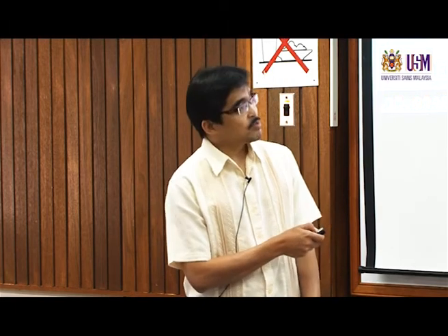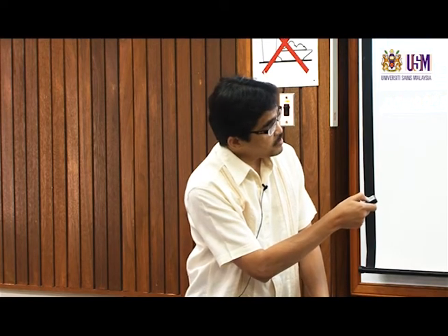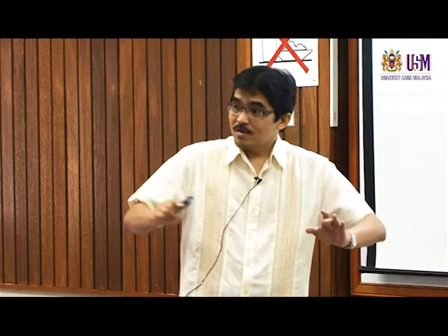In terms of structure recovery, based on this flow curve, we can say that sample B would recover its structure very fast. Therefore it would not spread much, because it will recover the original viscosity very fast compared to sample A. Sample A will take its time to recover, so its viscosity is still relatively lower than the original viscosity. And the final viscosity at the end of the shearing is much lower than sample B, so it will spread more.